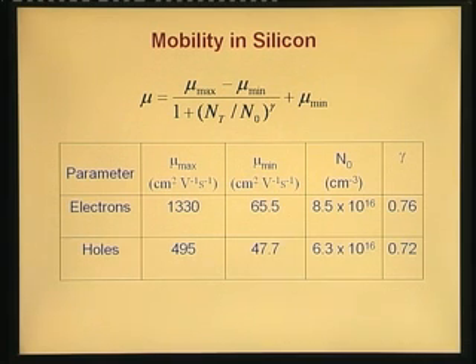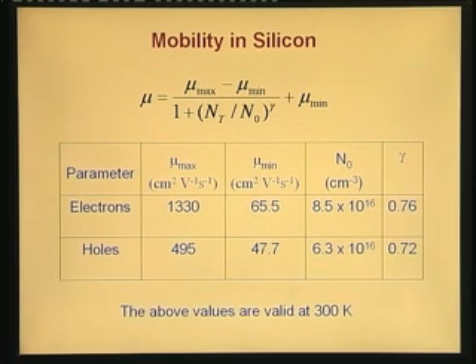For electrons and holes in silicon at 300K, the values are given in this table. So maximum mobility is 1330 for electrons and 495 for holes. Minimum mobility is 65.5, that is for very heavy doping levels for electrons, and 47.7 for holes. The unit for mobility is centimeter square per volt second. Similarly, the values of N0 and gamma are also given here. You can use this formula to find out the mobility for any given doping conditions at 300K. And then if you are interested in the mobility at any other temperature, you could use the formula that we showed earlier, that is mobility variation with temperature, and find out what the mobility is. We will consider a solved example to illustrate some of these ideas.